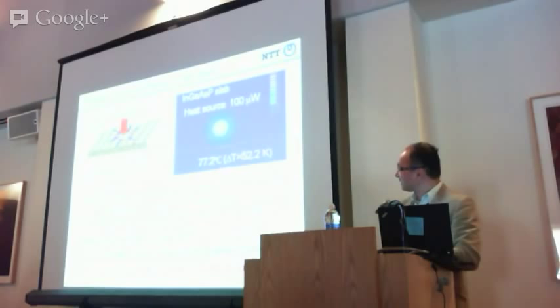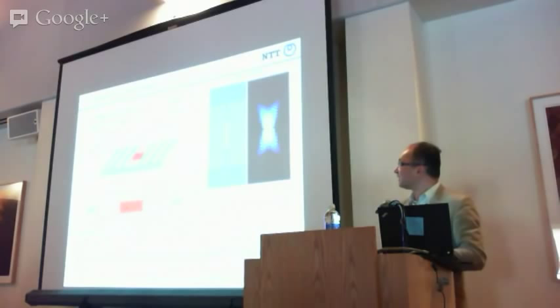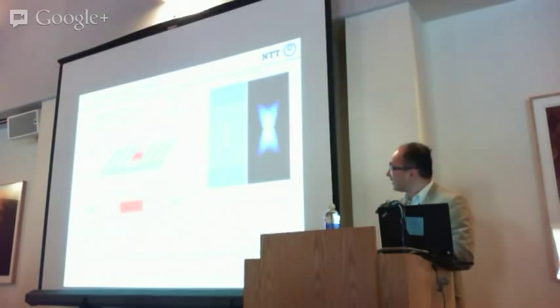And it is also that there is no carrier confinement structure in this device, as in previously developed photonic crystal lasers. So to solve these problems, we try to introduce a buried heterostructure in the photonic crystal nanocavity. There is an embedded active region, which is buried with an indium phosphide region. And this is a cross-sectional view.